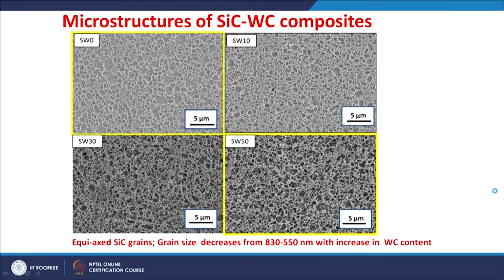The microstructure of these sintered silicon carbide composites exhibits almost equiaxed grains of silicon carbide, with very little presence of any elongated grains. These almost equiaxed SiC grain sizes decrease from around 830 to 550 nanometers with increase in the tungsten carbide content from 0 to 50%.